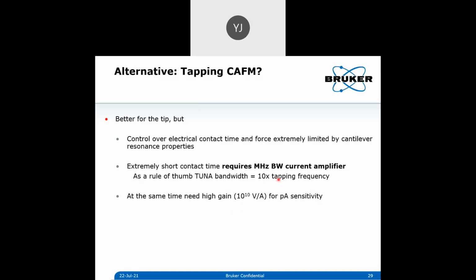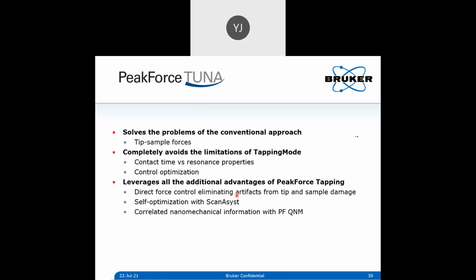Because we use PeakForce tapping, and we are very far away from the resonance of the cantilever, we are able to implement a very high bandwidth current amplifier with very high sensitivity, picoamp or femtoamp sensitivities, right? And we can use that to achieve conductive AFM, but basically in tapping mode. Because this is like tapping, you are doing oscillation, there is no lateral force and very limited tip-sample forces. You also have very good control of contact times, and you can optimize everything and get no artifacts because you directly control the force. You can self-optimize it, like the ones we show through ScanAsyst, and you can correlate it with the QNM data, right?